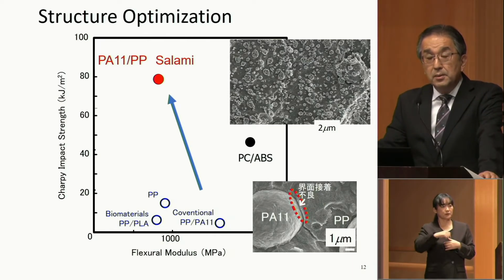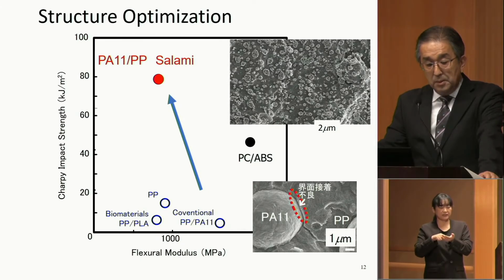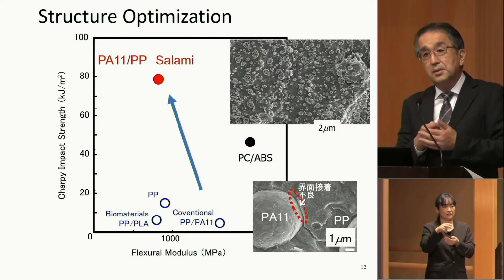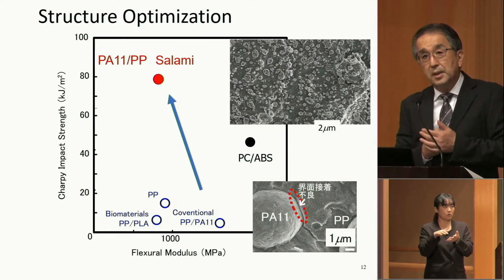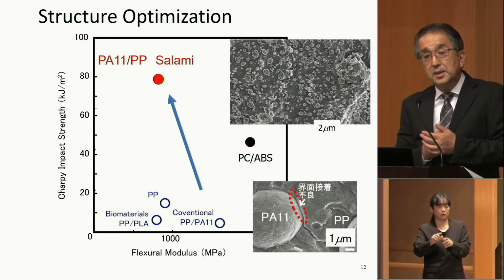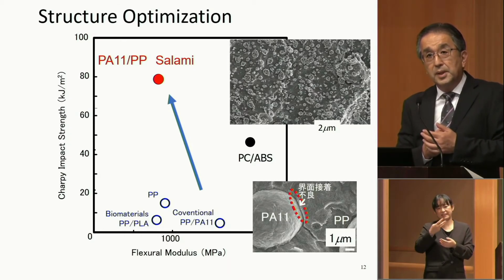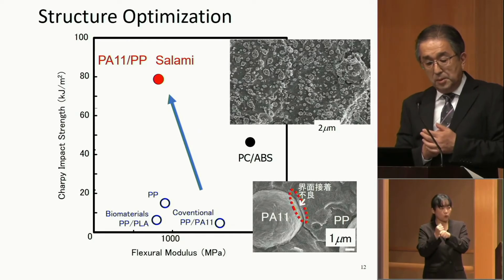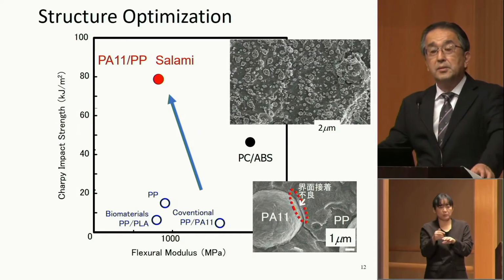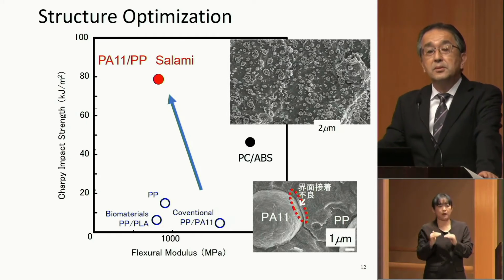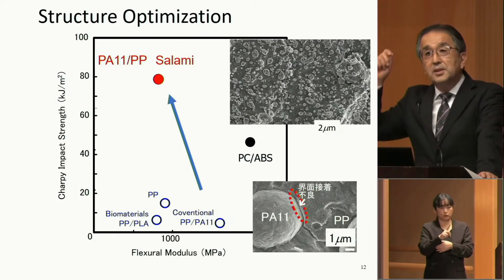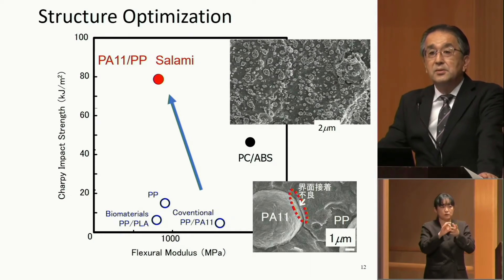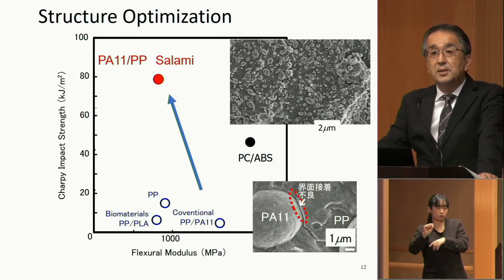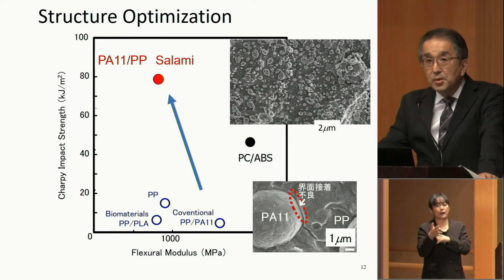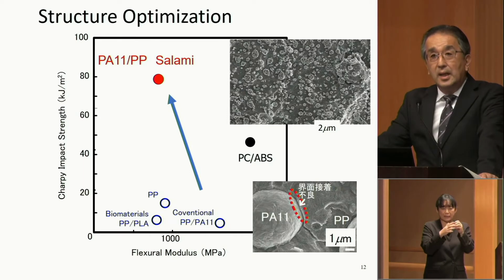The lower right is the mix of PP and PA11, and impact strength is very low. However, this newly developed salami structure drastically improves the impact strength to 80. PC ABS, polycarbonate ABS alloy, is often used for helmets, and it's about 50. So this new material has a higher impact strength.